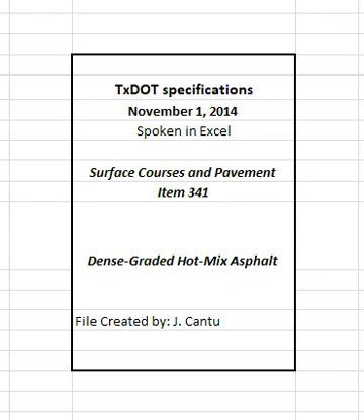4.4.2.2.7 Approval of JMF2. The engineer will approve JMF2 within one working day if the mixture meets the requirements in Table 5 and the gradation meets the master grading limits shown in Table 8. The asphalt binder content established for JMF2 is not required to be within any tolerance of the optimum asphalt binder content established for JMF1, however, mixture produced using JMF2 must meet the VMA requirements shown in Table 8. If the optimum asphalt binder content for JMF2 is more than 0.5% lower than the optimum asphalt binder content for JMF1, the engineer may perform or require the contractor to perform TEX 226F on Lot 1 production to confirm the indirect tensile strength does not exceed 200 psi.